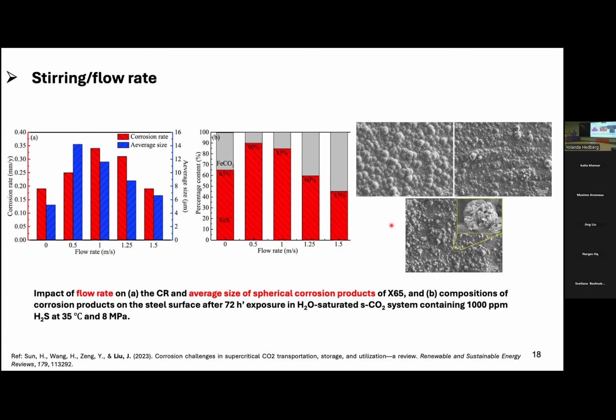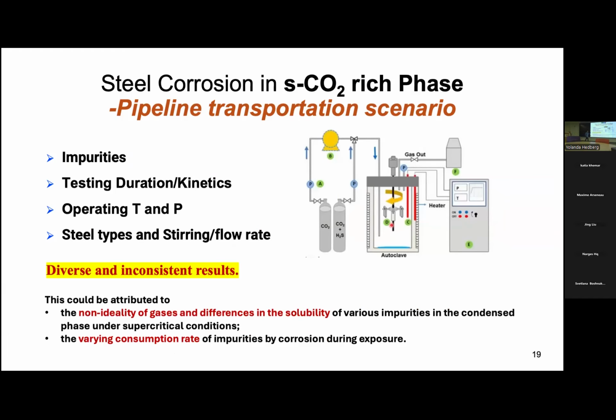For example, as I said, the 10-hour versus 100-hour result, and even at the same impurity level, different groups show different data. In my understanding, this part of work, even though over 300 papers have been published in this area, we cannot simply look at them and follow. One reason is we don't have an ASTM standard, but we still need to understand why they are different. I think the testing duration is one matter because people tested different durations.